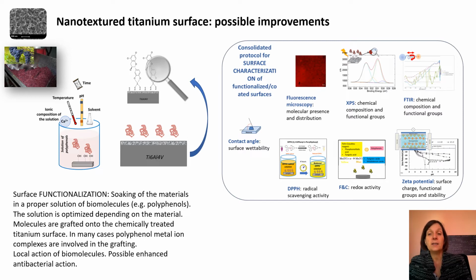And by XPS we can also define the type of the chemical bond between the polyphenols and the surface. And we observed that in some cases we have an improvement by using calcium ions during functionalization, and so we have a link that is a strong chemical bond through the calcium ions. And we tested the release of the polyphenols. We can see that we have some release in some hours, but we have also a very long life of this coating for up to 1 month at least because of the strong chemical bond.